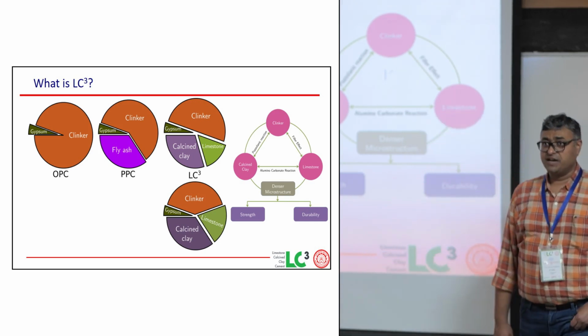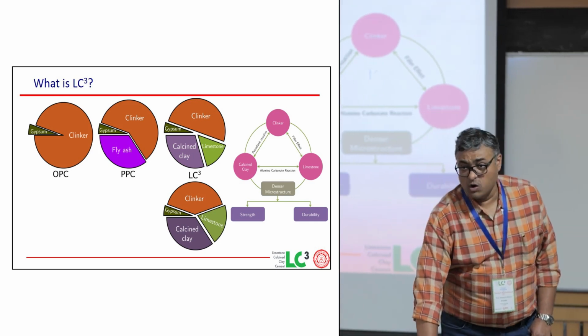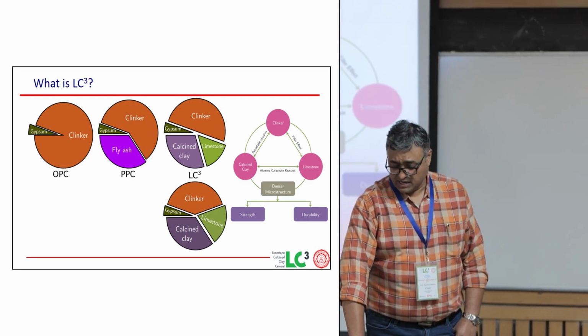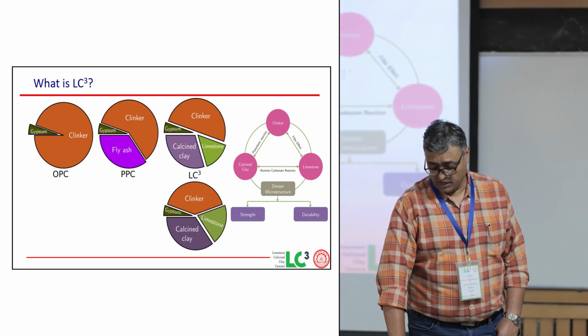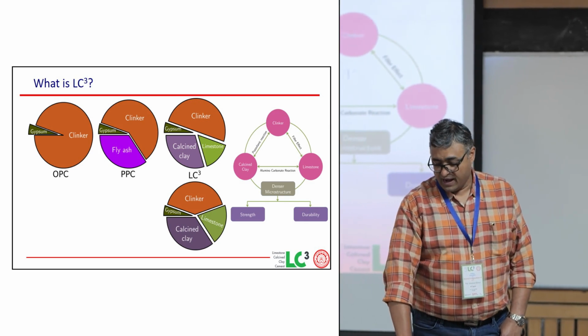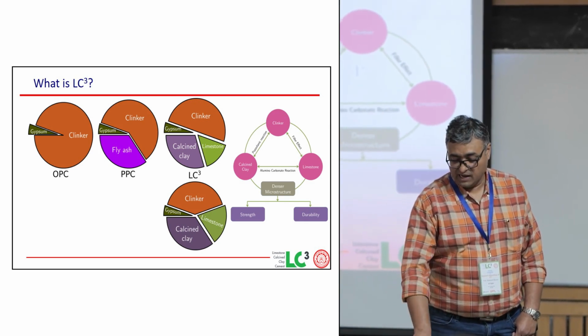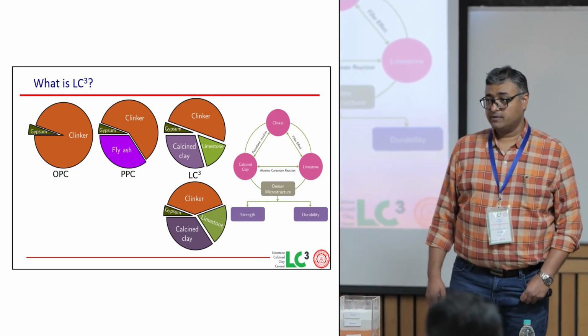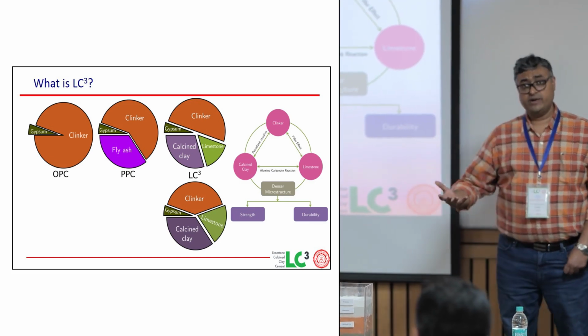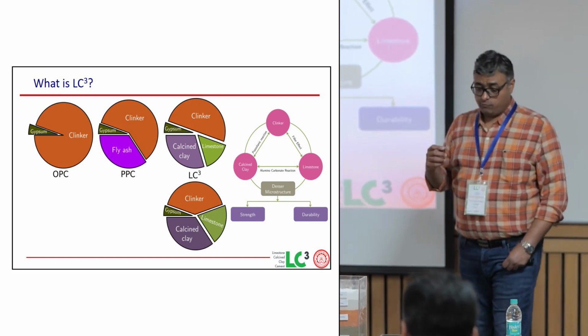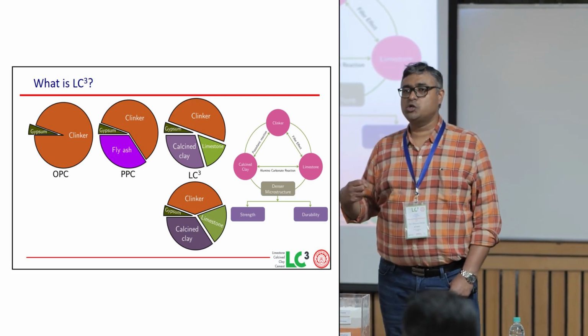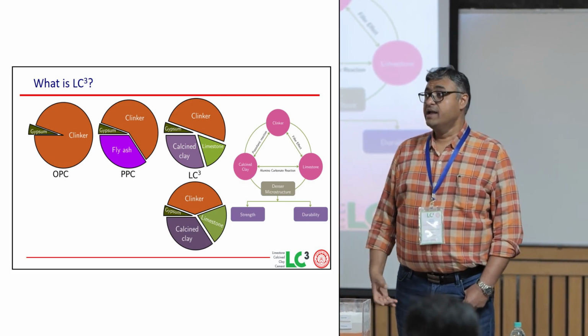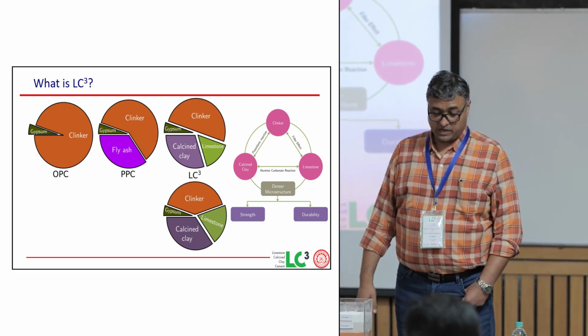The idea of LC3 is that you can reduce the amount of clinker in the cement. Currently, according to the standards that we have, you can have 50% clinker, and the rest of it would be calcined clay, limestone, and gypsum. What we are working on right now, and you'll see a lot of results from that, would be cements that can have as low as 25-30% clinker and still give you the kind of performance that you would expect.